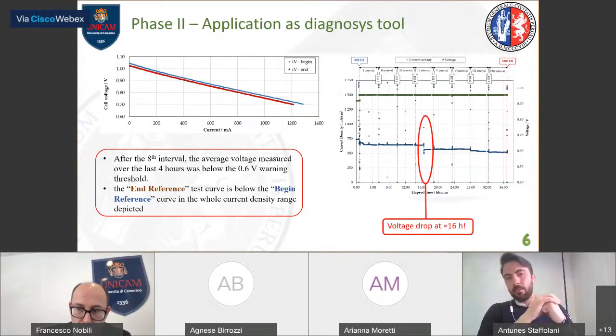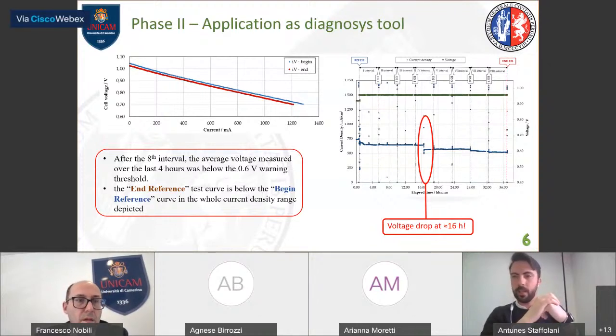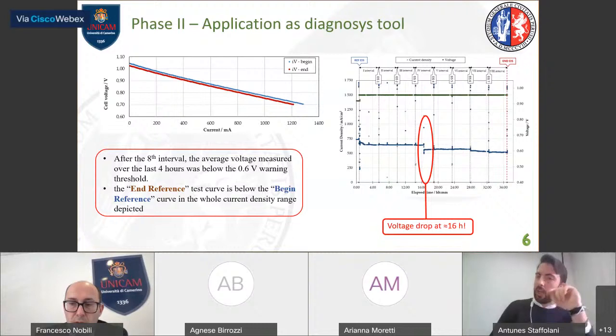And as you can see from the polarization curve, before and after the stress test, there was a small gap, so the polarization of the cell increased, especially at the high current points. And looking at the potential versus time profile, there was a voltage drop exactly at 16 hours. And at 46 hours, we stopped the experiment since the cell reached the threshold value of 0.6 volt.